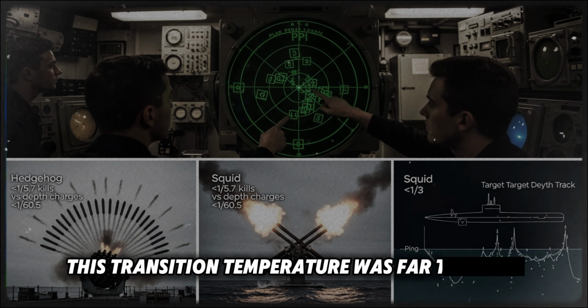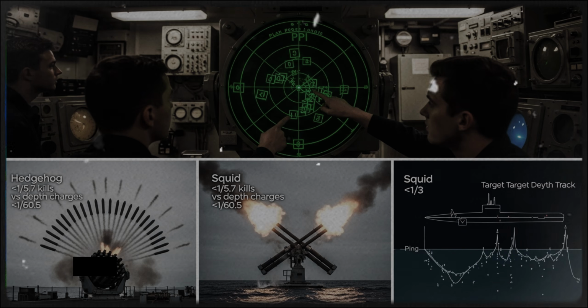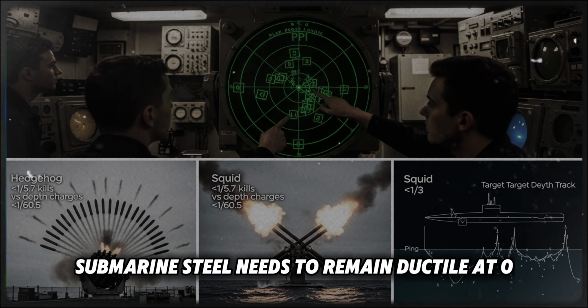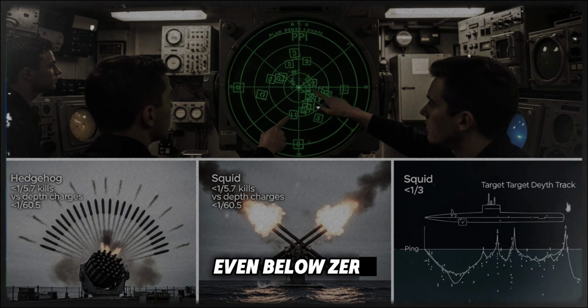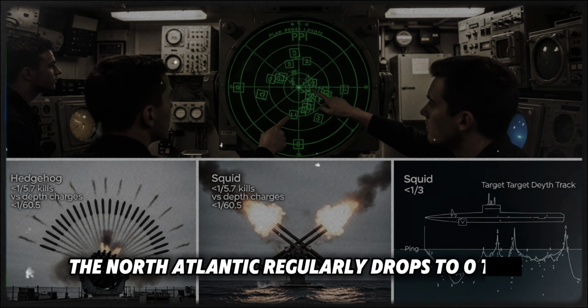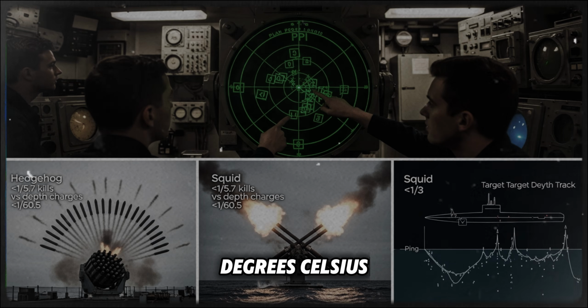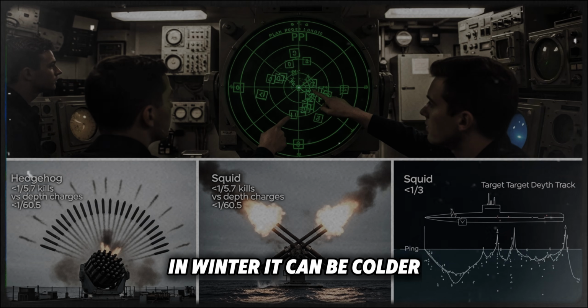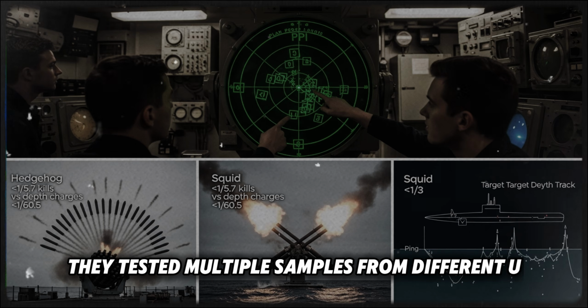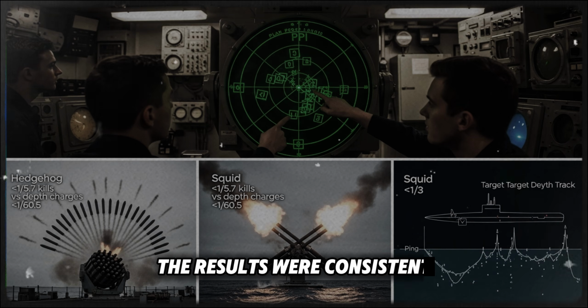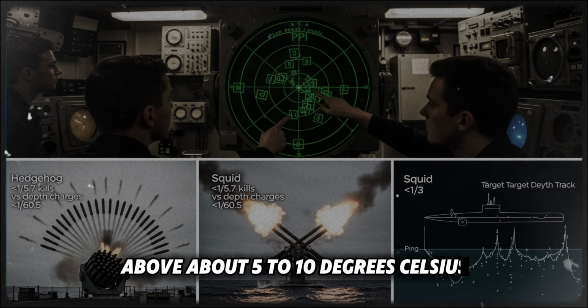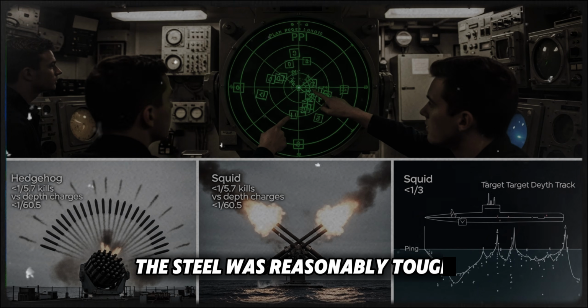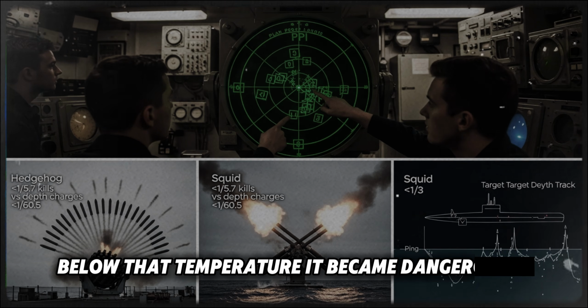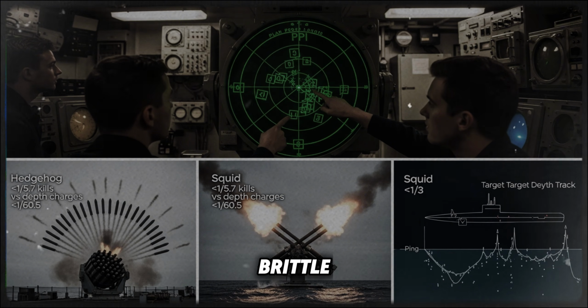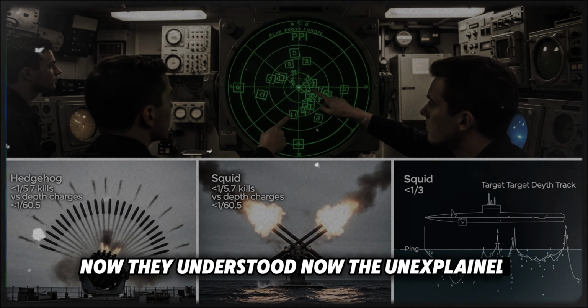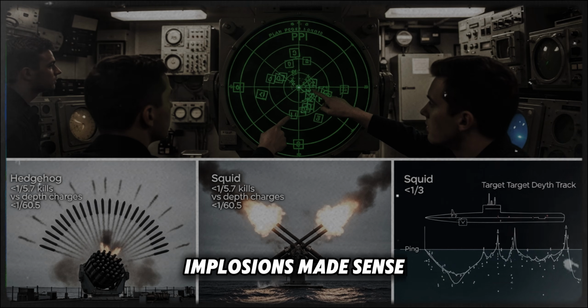This transition temperature was far too high. Submarine steel needs to remain ductile at 0 degrees Celsius, even below zero. The North Atlantic regularly drops to 0 to 5 degrees Celsius. In winter, it can be colder. They tested multiple samples from different U-boats. The results were consistent. Above about 5 to 10 degrees Celsius, the steel was reasonably tough. Below that temperature, it became dangerously brittle. Now they understood. Now the unexplained implosions made sense.